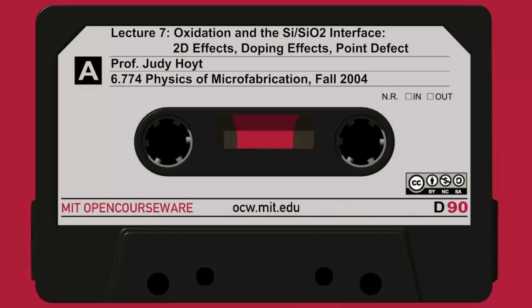So a tall pillar, say a couple microns tall, but where the starting diameter of the pillar would maybe only be a couple hundred angstroms, say 200 angstroms. So it starts with this little needle of silicon. And you can do a 200 angstrom pillar or a 300 angstrom diameter pillar with a very good electron beam lithography machine. At least in those days, that's about as small as people could get, a couple hundred angstroms. You pattern the dot, and then you etch the silicon into a nice pillar.